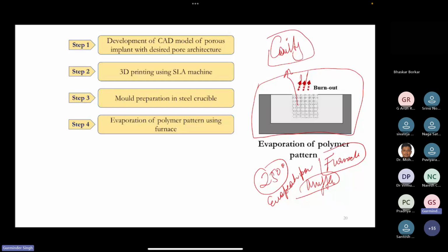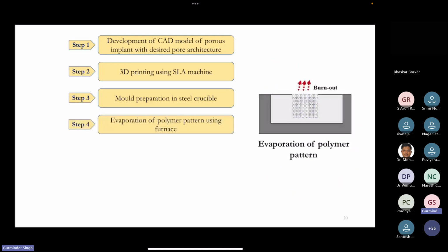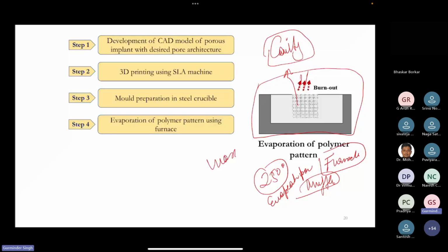It will give you a cavity, and the first important thing is here. The polymer which we have chosen for 3D printing was a wax type of material because it has a good advantage: you can go directly from solid state to vapor state. You can control it and keep the liquid stage to a minimum time, so it will not give you cracks in the investment area. So you can directly make a crack free mold.